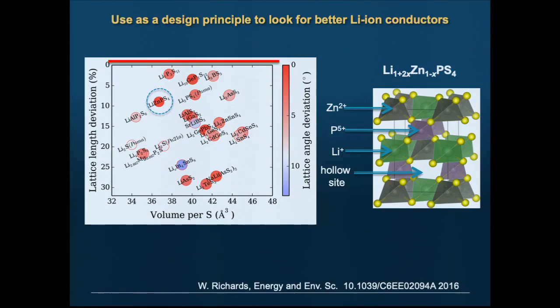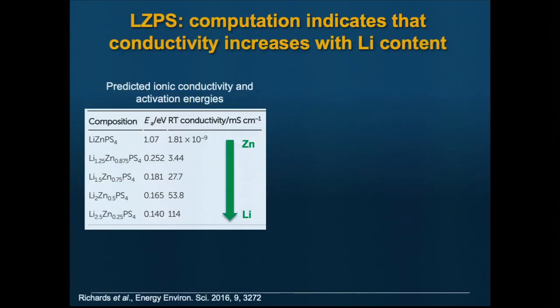By itself, it's not a good conductor. You have to put in carrier, so you have to lithium dope it. And we predicted that depending on the amount of lithium doping, we could get as high as 100 millisiemens.